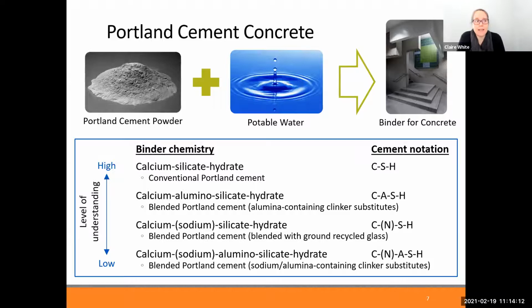Concrete has one phase that essentially gives the concrete strength, and it's called calcium silicate hydrate gel. And people are still debating what is the structure of this gel, what are the properties of this gel, even though concrete's been around for 150 years. So it's a complex phase, it's disordered, it does have some ordering in there, but it's also difficult to study in concrete because there's over half a dozen phases that exist in concrete. So trying to isolate the calcium silicate hydrate gel is difficult.